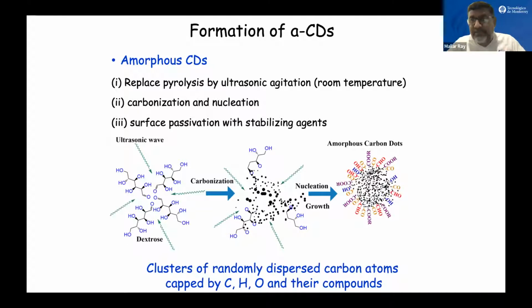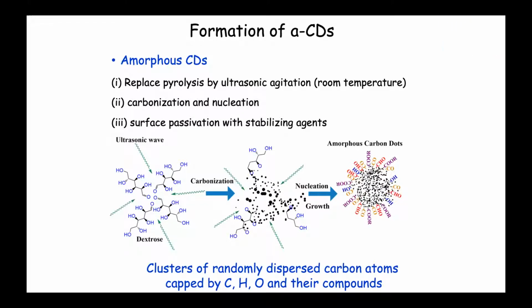The simple thing is we don't go high up in that energy where we can push these carbon atoms to reorient and get a crystalline structure in them. So we do the whole experiment in a comparatively lower energy regime. The particular experiment that led us to form these amorphous clusters was done at room temperature.